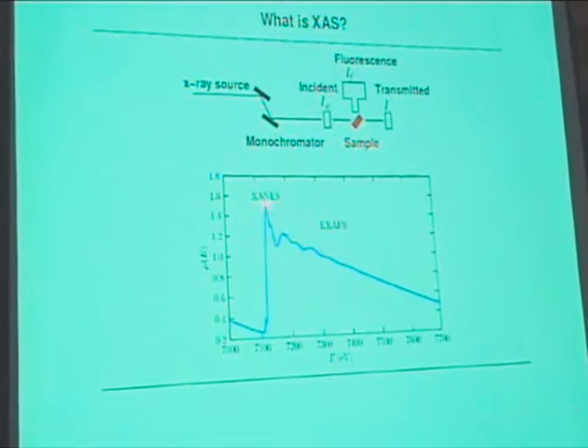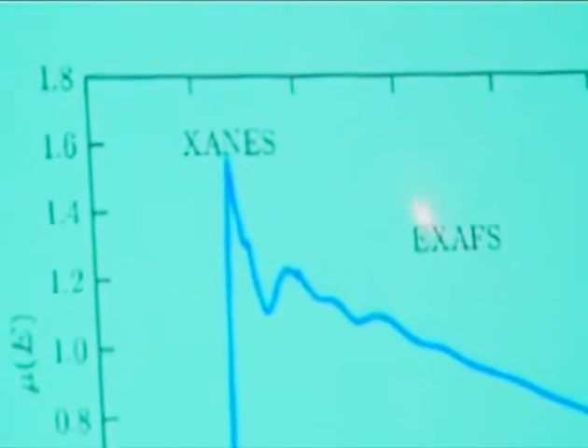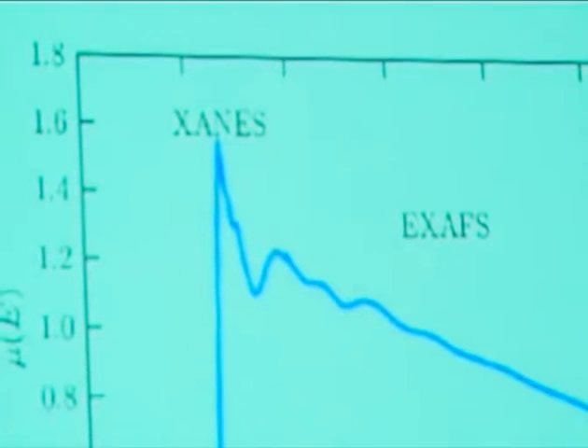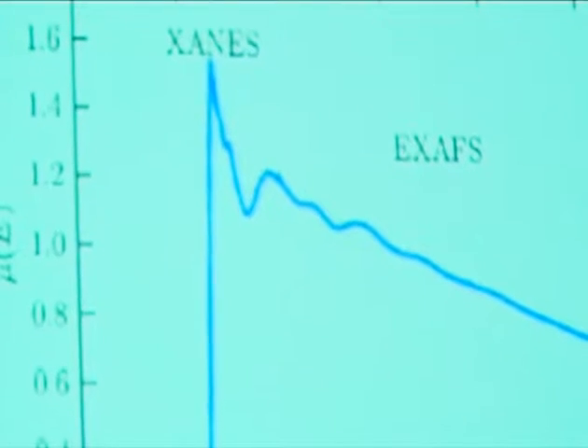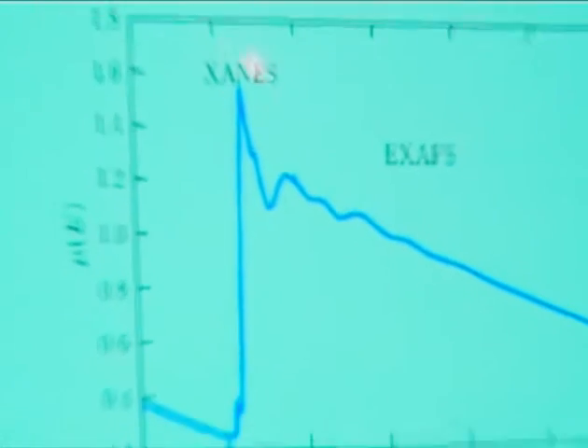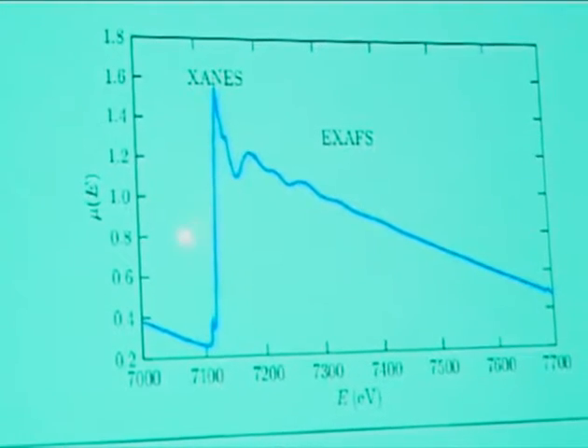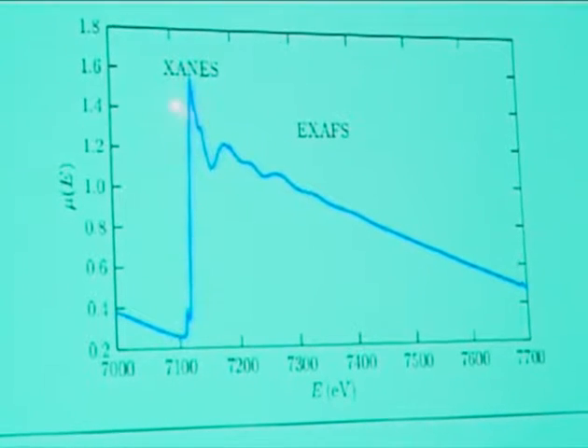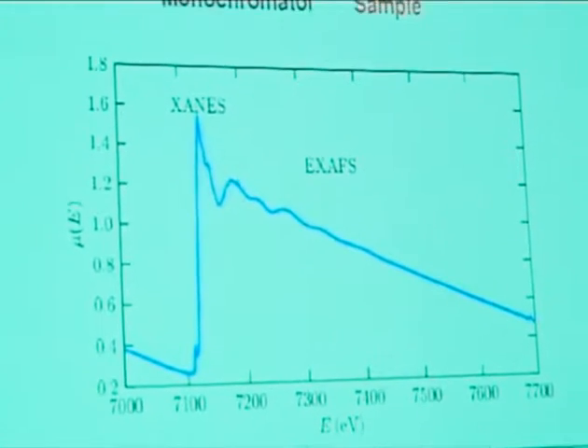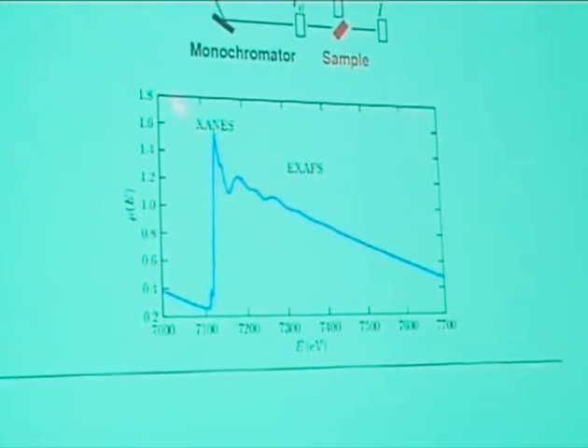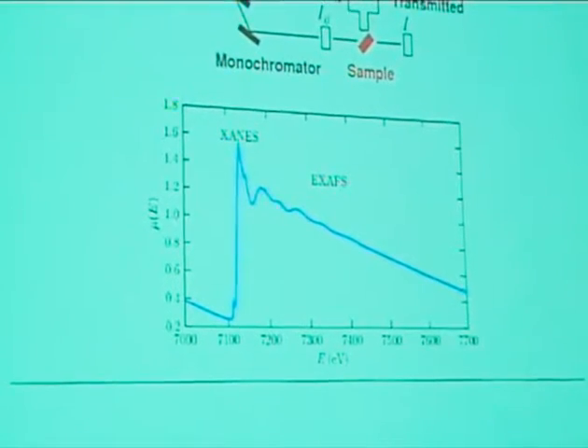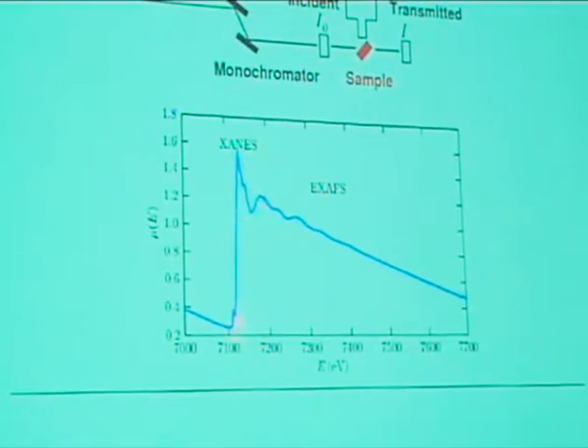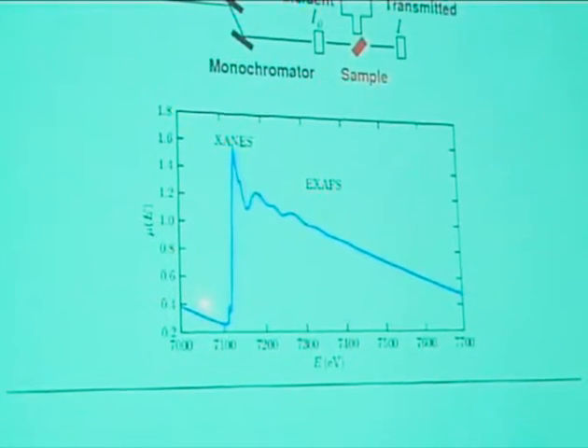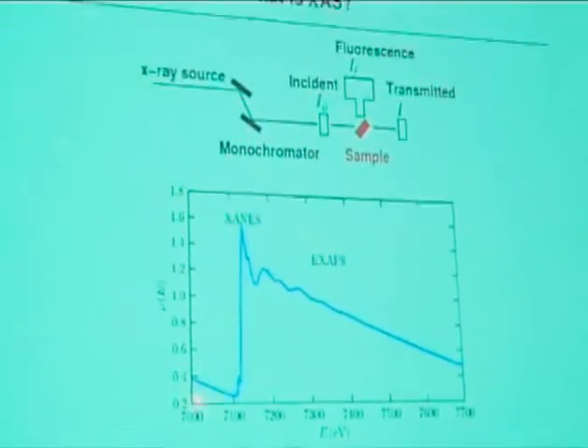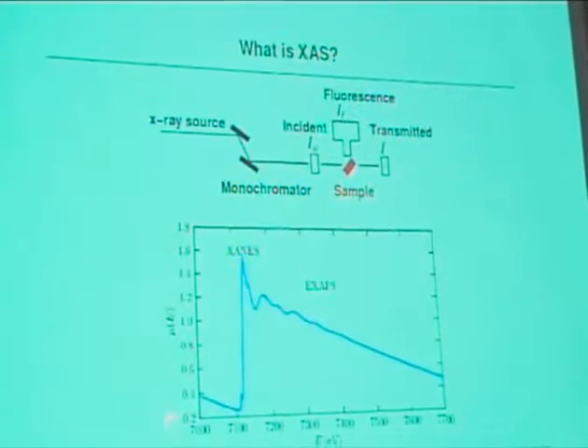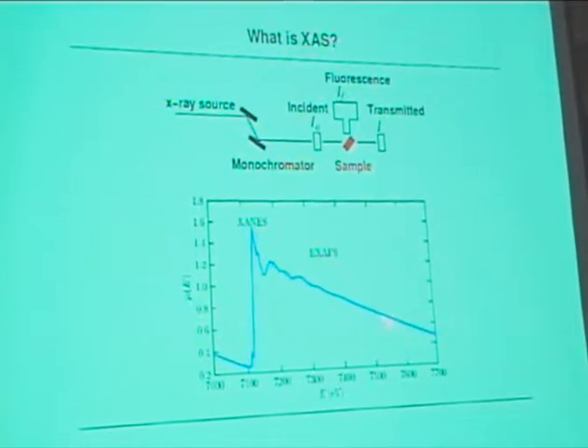Now, very close to the edge, we give it a different name. It's not called extended X-ray absorption fine structure. Extended, because as you see, it can go on over 1,000 electron volts, a lot of energy. But close to the edge, we have the X-ray absorption near edge structure. It has also been given other names, but I will call it XANES. Here, the electron is not going out yet as a free wave. It may go to bound levels. So it's like normal spectroscopy in the UV or whatever have you. It's from a bound to a bound level. And I'll show you later some examples of information that we can get out from this region as well. Here you don't get structural information, you get spectroscopic information, which you can use in an analytic way. Here, in this extended region, you get the structural information.